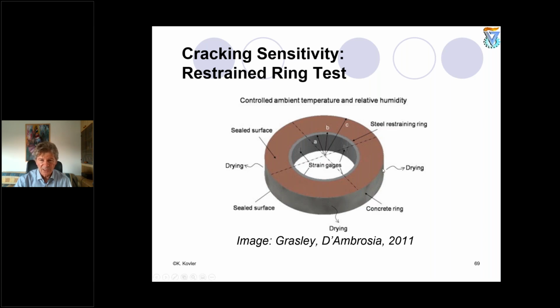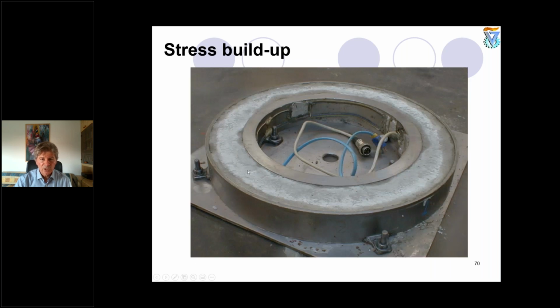When we demold the specimen from all the sides, from above and from the sides, it's shrinking towards the core. And this is just a picture illustrating the appearance of the concrete ring. You see, it is located between the two rings: the internal ring, which is responsible for the generation of the tensile stresses in concrete, and the external ring, which can be demolded completely if we would like to simulate drying shrinkage. If we don't demold, if we work with sealed concrete specimens, this is a simulation of autogeneous shrinkage. Autogeneous deformation should be measured under sealed condition and under isothermal condition. This is by definition. Please look into the report of our technical committee.